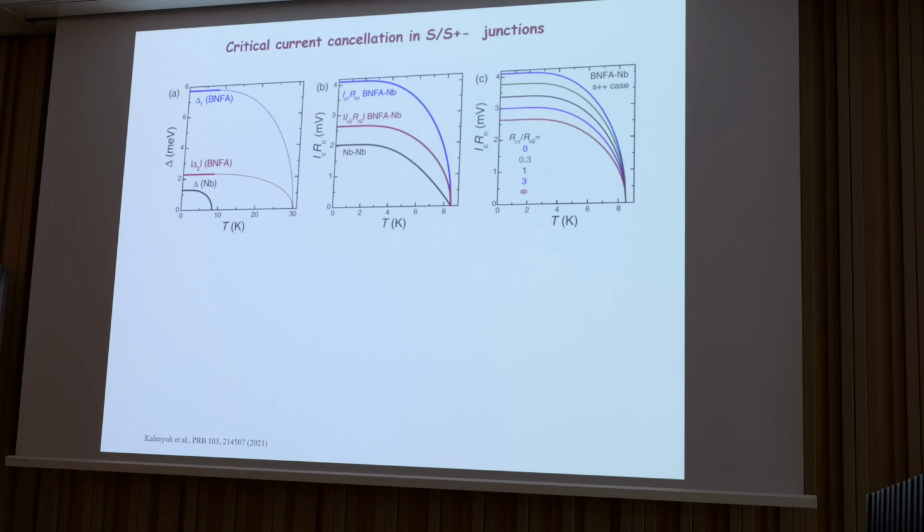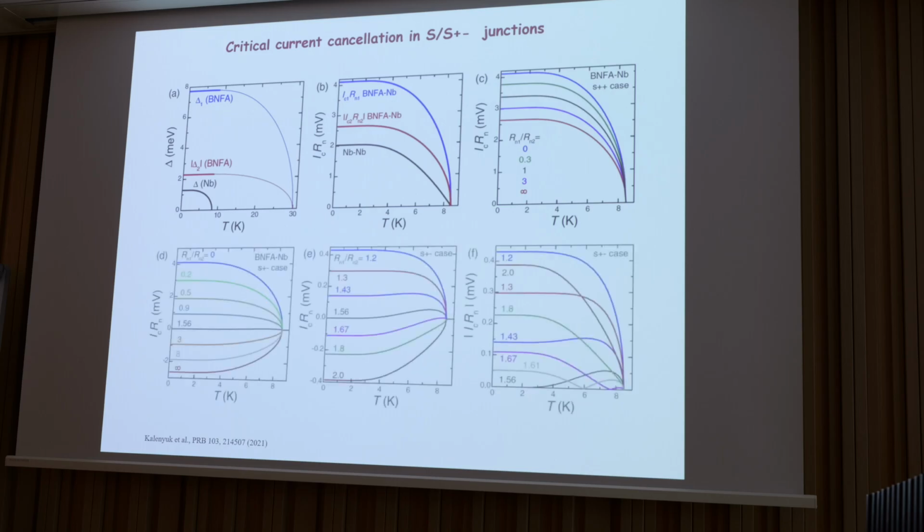But if you start to subtract them, if you assume that there is sign reversal between the bands, then the situation becomes much more interesting. So now we go from one band, which let's suppose has a negative sign, while the other is positive, and then we start to compensate them. When we add them, we subtract the total current. This is the result of the temperature dependence. The complete compensation appears at about 1.56 ratio of the transparencies between them.